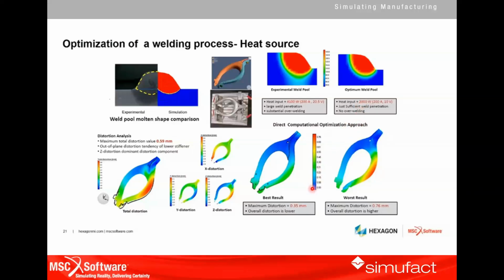So we can see the worst result here using the power of 4,000 watt. And once they optimized the heat and weld pool penetration, we are able to get the optimized result, that is, with less distortion. Overall distortion in this case was around 0.76 mm, and it came down to 0.35 mm.